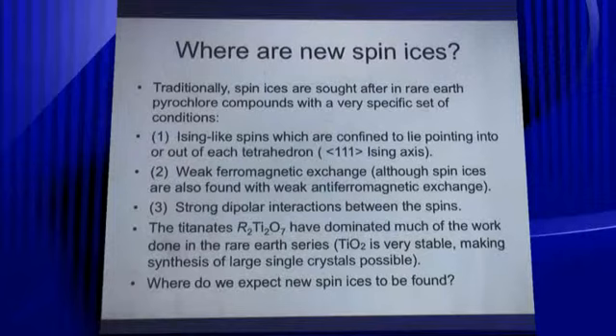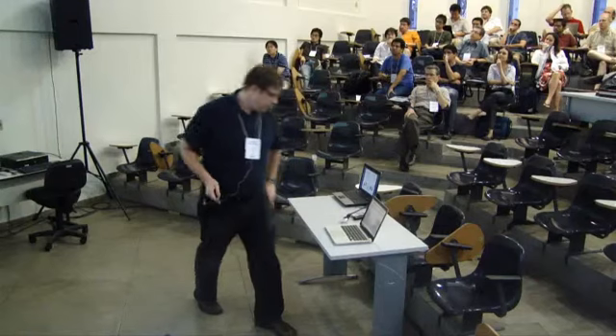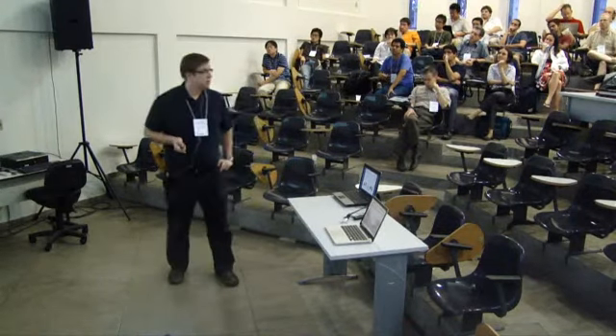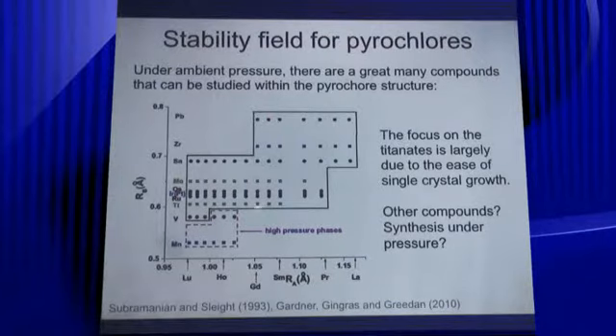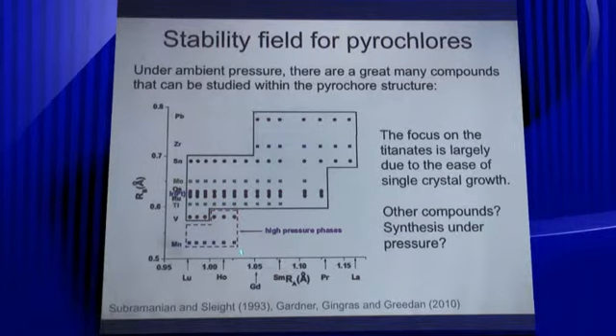So where do we expect new spin ices to be found? This stability field has been presented, I believe, by Michel at one point. This is looking at the A2B2O7 chemical structure, where you expect to see different types of phases forming. This is under ambient pressure, and these are some high pressure phases here. As I mentioned before, among the titanates you can only make certain pyrochlores here. So these ones, for example, the praseodymium titanate case doesn't exist. The praseodymium stannate exists, for example.